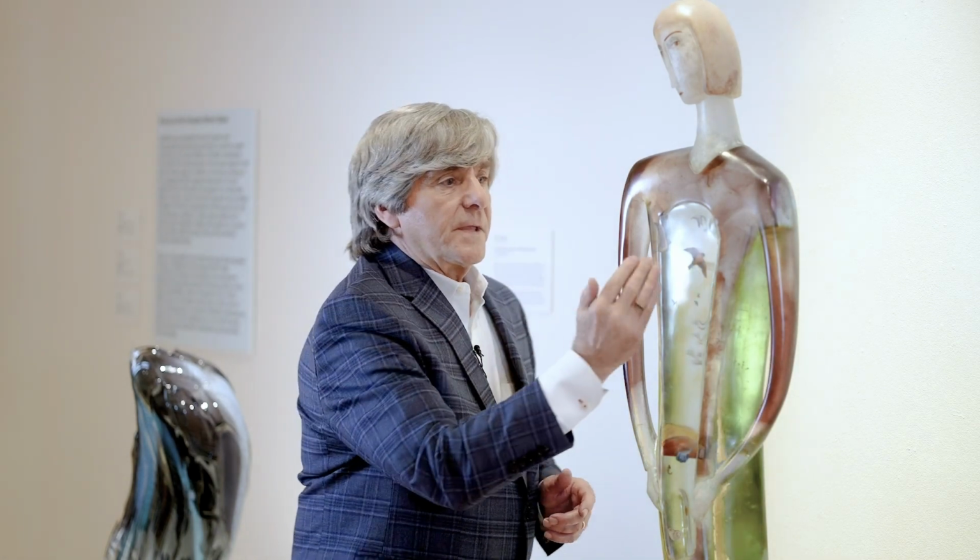Now, I think she actually, in this case, didn't pour it separately, and I say so because there's a slight outward curve in the chest and the abdomen that in a pour, in a cast, would be very difficult to do without the gravity of the molten glass laying it flat. Now, you might do that and carefully grind this down, but you also could do it by casting it separately, but you would have made the mold from the concave section here so that the mold is going to produce exactly, with every nuance and ripple, the piece that we're going to tuck in. We'd tuck that piece in, you'd probably pin it with some molten glass and then put it back in the oven.